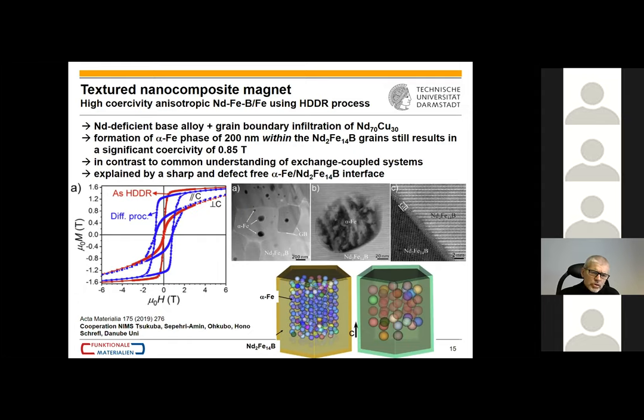So here we propose a new concept in this joint work with NIMS Tsukuba, where we apply a reversible hydrogen absorption and desorption process to a rare earth deficient base alloy. So that tends to have some excess of iron. And you can see here in the TEM microscopy that we manage to distribute iron precipitates within this hard magnetic matrix. And you also see, if you're familiar with exchange coupled systems, that this iron precipitate is actually significantly larger than in an exchange coupled system, where we usually aim at 10 nanometer grain size.